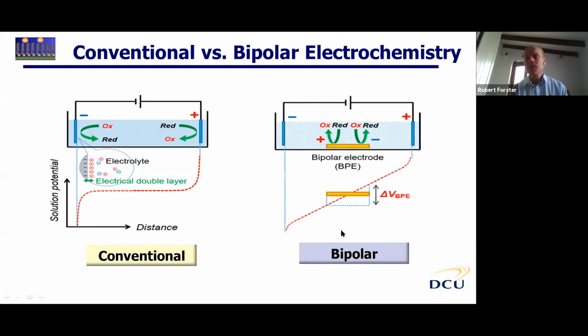In contrast, when we have a wireless or a bipolar, an open bipolar cell, what we're doing is we're using a pair of feeder electrodes, and that pair of feeder electrodes set up an electric field in the solution. And now if we place an electronic conductor in that solution, it assumes an equilibrium potential, but one end will have a potential that is different from the solution potential. We'll generate an oxidizing potential at one end of the electrode.